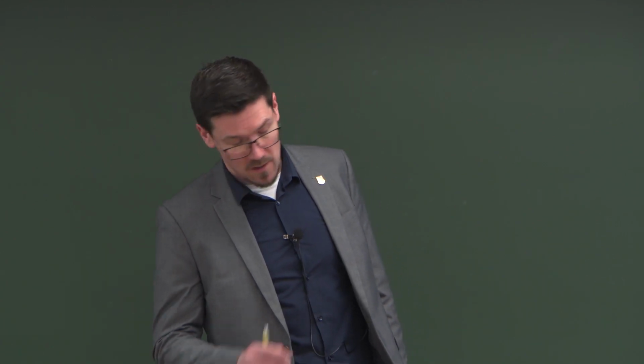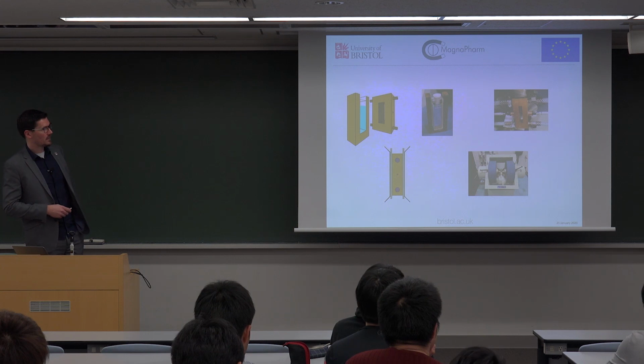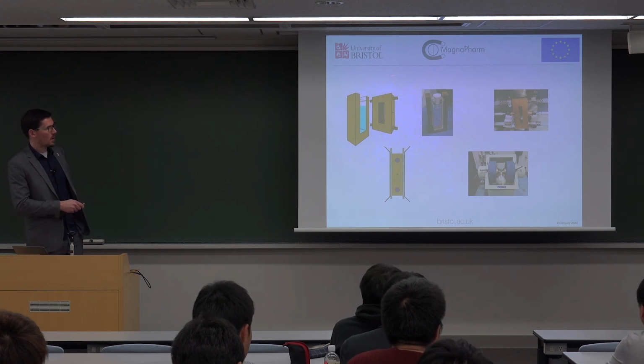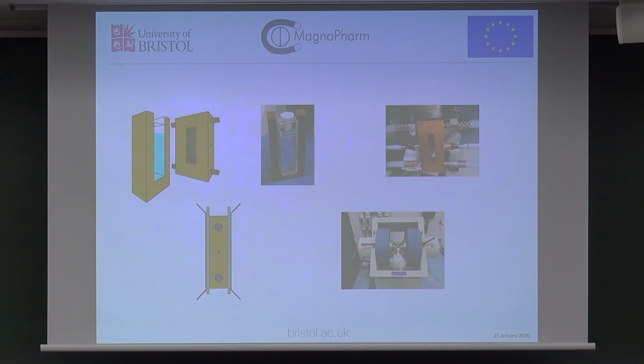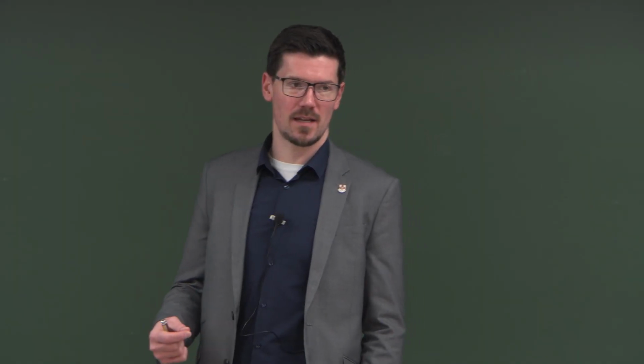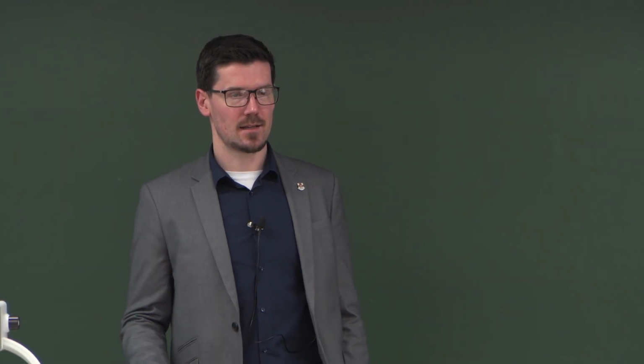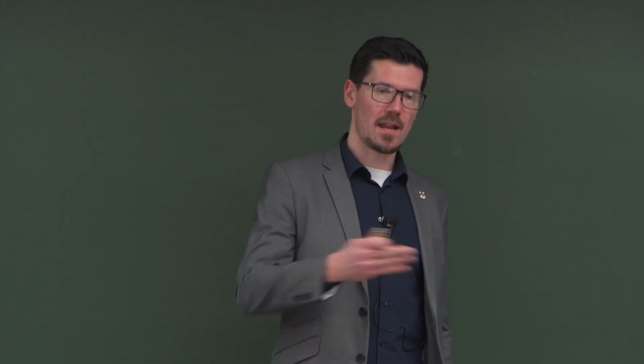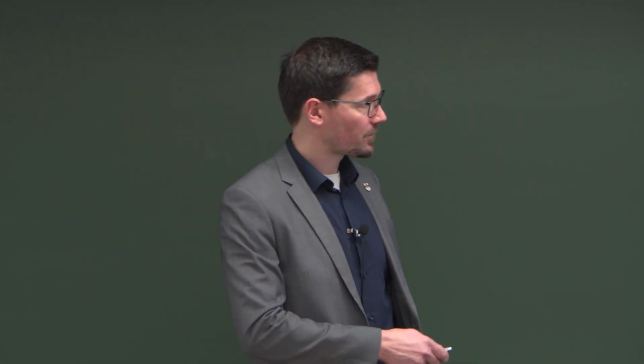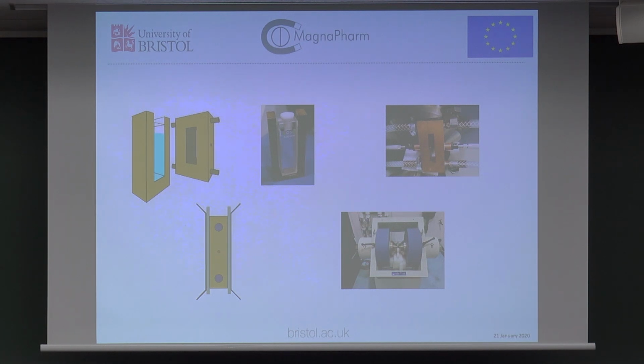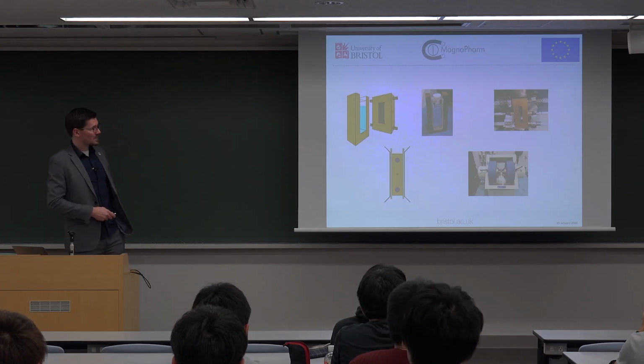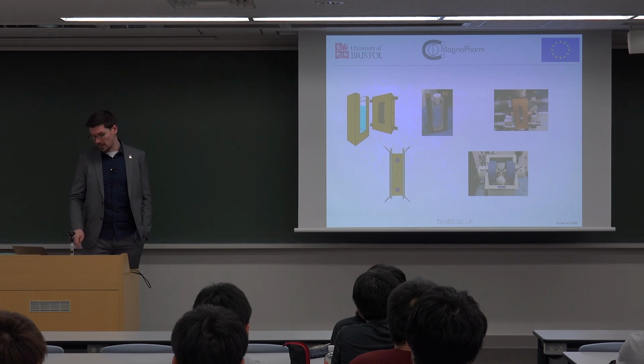So back in Bristol, this is where we designed this piece of kit. This is basically a copper block with like a horseshoe-shaped holder. We slot the cuvette in like this. We push it into the copper block. This is a water pipe in. This is a water pipe out. So we flow water through the copper block nice and fast so we can keep the temperature nice and stable. So we use a water heater to control the temperature of the water, and that water then controls the temperature of the copper block. We've also got an optical cable going through the middle, so we can also, again, measure the point of crystallization. But when we put carbamazepine in a cuvette, in the magnet, what do we get?